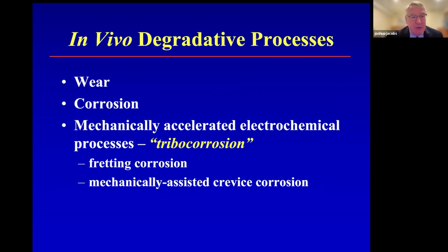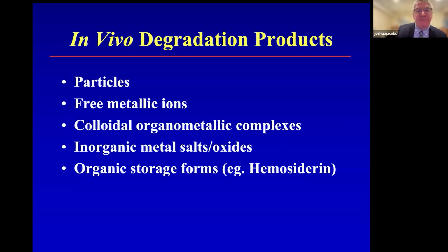Because not only do metal components wear from the mechanical and tribological interaction between the two surfaces, metal components uniquely undergo a process of corrosion. And then there are synergistic interactions between corrosion and wear, causing mechanically assisted electrochemical processes, which we call tribocorrosion, things such as fretting corrosion and mechanically assisted crevice corrosion, both of which are very important in the performance of the devices, as we'll see.